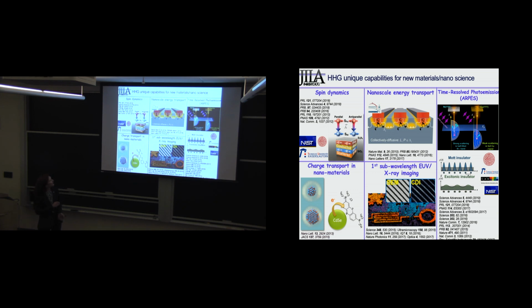And this was sort of an interesting one. It was on nanoscale hotspots. How did they cool? And the lore was that if we think about bulk cooling, if you want to cool something down, you're surrounded by a lot of cold material. And it was well known that if you had a nanoscale hotspot, it had a hard time connecting to the full phonon spectrum in the substrate, because if the size of the hotspot was smaller than the average phonon mean free path in your substrate, the heat transport would not be efficient.